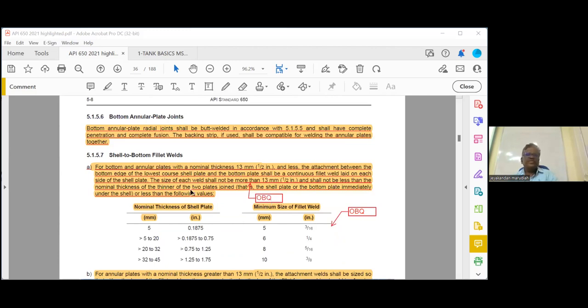Then shell to bottom fillet welds. When you are using a shell to bottom, see if you take a tank, which joint is more critical to the storage tank is shell to bottom joint. That joint is highly critical because there will be more stress acting there. Okay, that joint is critical. What should be the fillet weld size of that shell to bottom weld? Shell to bottom, I told it will be a double-sided fillet weld. For high thickness, we will prepare an edge preparation also.